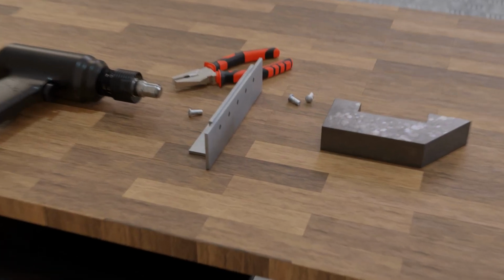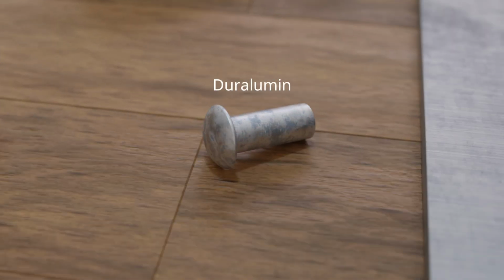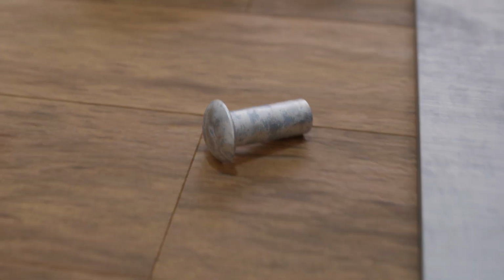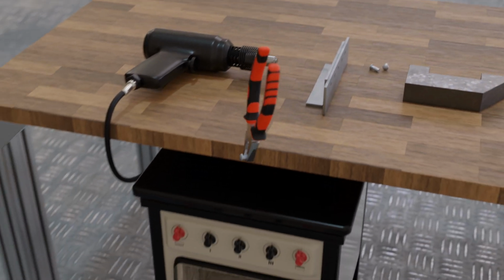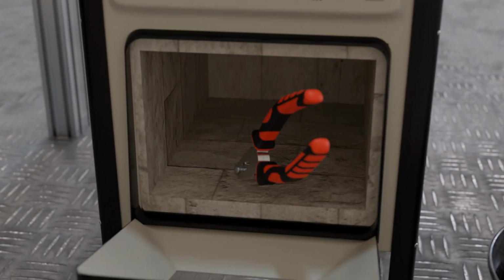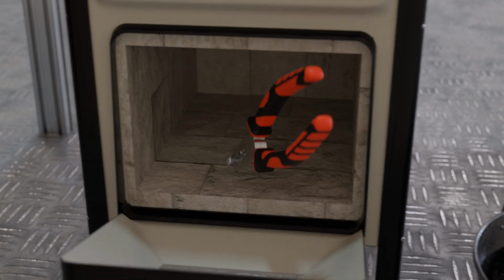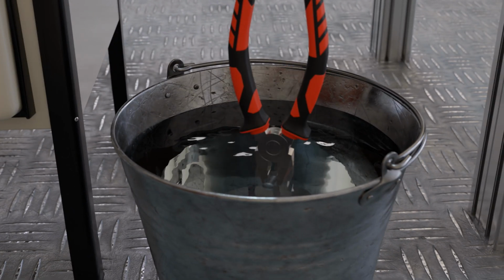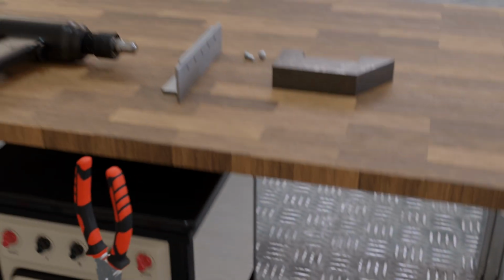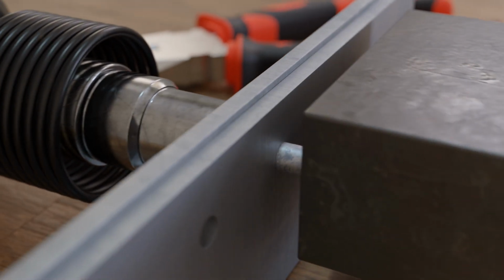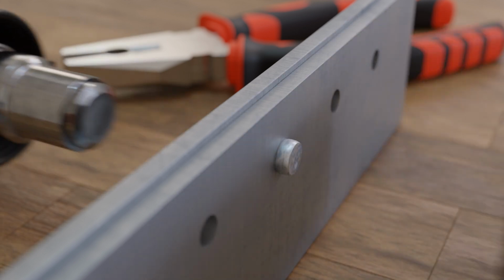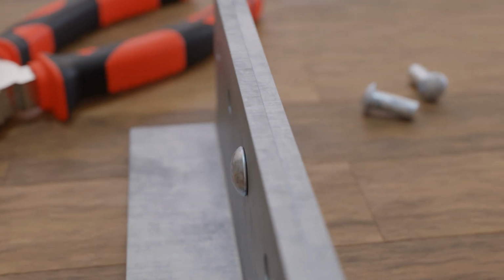This principle is used, for example, with rivets made of duralumin, an alloy of aluminium, copper and magnesium. The rivet is first heated to about 500 degrees Celsius. This is called solution annealing, so that the alloying elements are first completely dissolved. Through rapid cooling, these alloying elements now remain forcibly dissolved in the lattice of the base material. In this state, the rivet is soft and easily formable. Over time, however, precipitates form from the supersaturated state. This process is called aging. In this way, a duralumin rivet will reach its maximum strength after a few days.